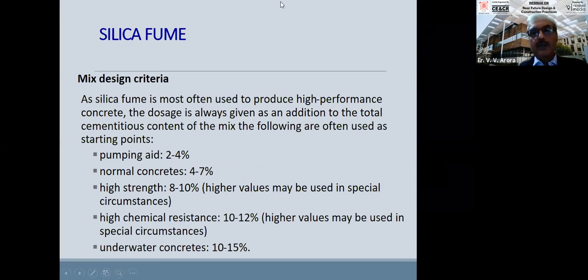The guidance on this is being added in mix design codes, IS 456 and IS 10262. Generally it is being used in this range: 2 to 4%, and 4 to 7% for normal concrete, 8 to 10% for high strength concrete, and for high chemical resistance, 10 to 12% also.